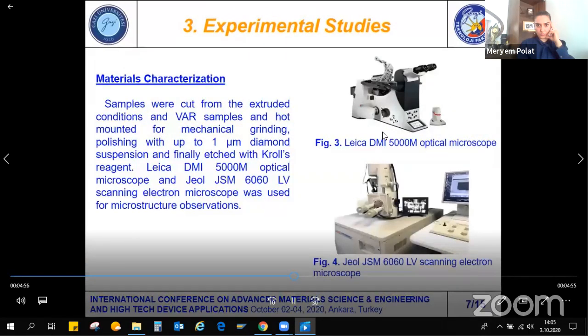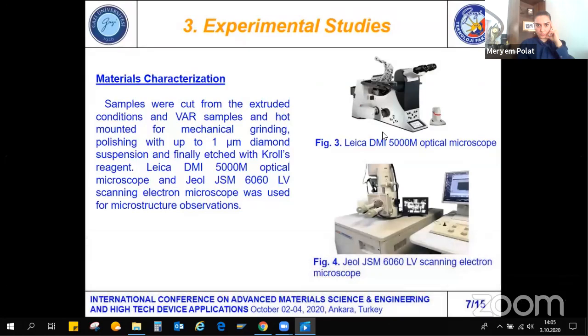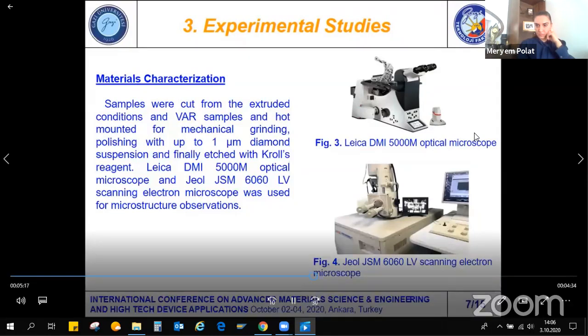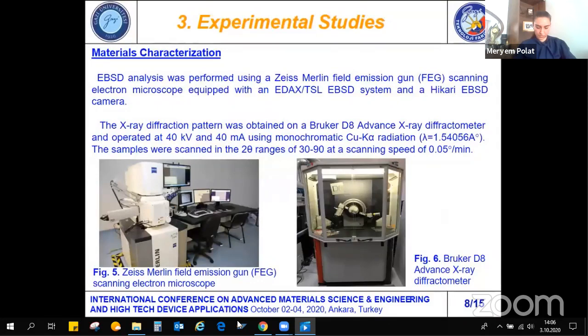Materials characterization. Samples were cut from the extruded conditions and vacuum arc remelted samples and hot mounted for mechanical grinding, polishing up to 1 micron diamond suspension, and finally etched with Kroll's reagent. Leica DMI 5000M optical microscope and JEOL JSM 6060 LV scanning electron microscope were used for the microstructural observation. Electron backscatter diffraction analysis was performed using a Zeiss Merlin field emission gun scanning electron microscope equipped with EDAX TSL EBSD system and a Hikari EBSD camera.